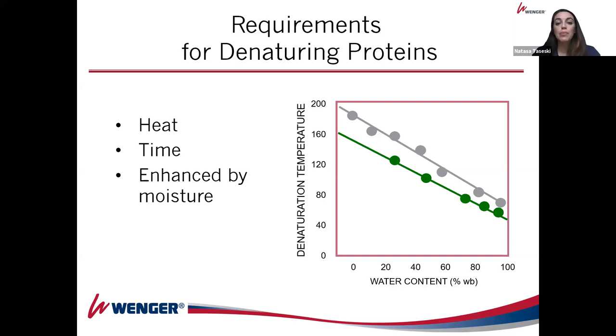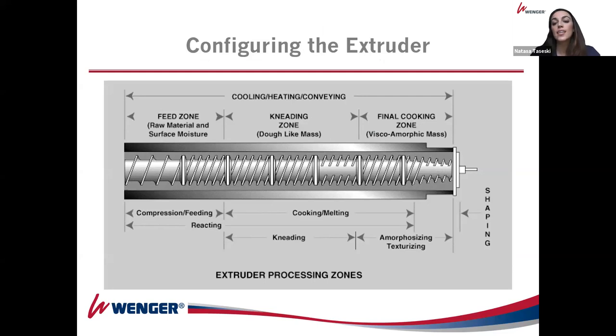So when it comes to what happens inside of the extruder, if we start to look a little bit more in detail, I'll do a little bit of a comparison between the dry texture proteins and the high moistures as well. But when you look at the extrusion process, you have a feeding zone at the very start where raw material is entering the extruder and has been either pre-hydrated in the preconditioner, or we're introducing some moisture at the beginning stages of the extruder. Then it goes through a kneading zone and a mixing zone, and then finally through a final cooking zone. So if you look initially, your product is typically flowable and has granular or powdery consistency. And then as you start kneading the zone, you essentially get a dough-like mass. So relatively viscous material. And as you get further down into the cooking zone, you get a properly melted viscous material that is able to be pushed out through the die and shaped.